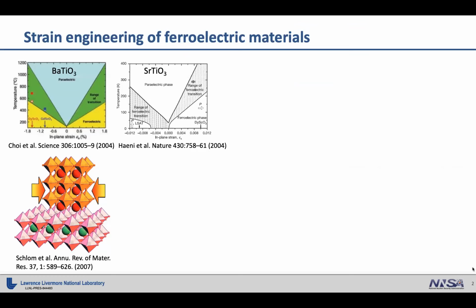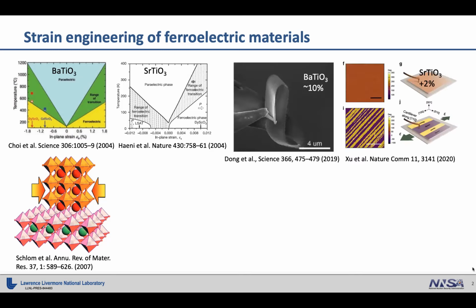As we know, the mechanical strain can have a huge impact on ferroelectric material properties. And the ferroelectrics community has been playing around with the strain engineering game for more than 2 decades. The early work, which I highlighted 2 of here, is one, to increase the Curie temperature and the ferroelectric property in barium titanate when grown on a substrate by strain engineering. And another one is to make the room temperature incipient ferroelectric STO ferroelectric, also using the misfit strains.